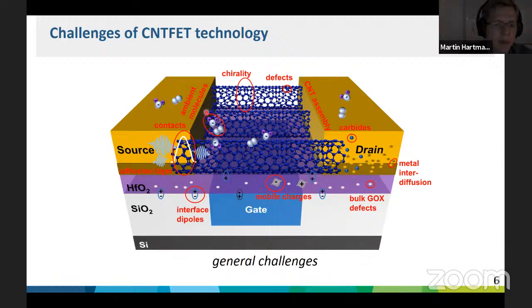And this doping is a big topic now for 1- and 2-dimensional materials, because when you want to dope them, you cannot do it by direct chemical doping, because then you usually destroy the nice crystalline structure and you don't have the excellent properties of the nanomaterial anymore. So you need to think of electrostatic doping. And you can do this intentionally or unintentionally due to mobile charges, static charges in your oxides, in your layers that are around the CNTs. You can have interface dipoles if you have an interface between different materials. And all of these charges and dipoles electrostatically dope your CNTs.